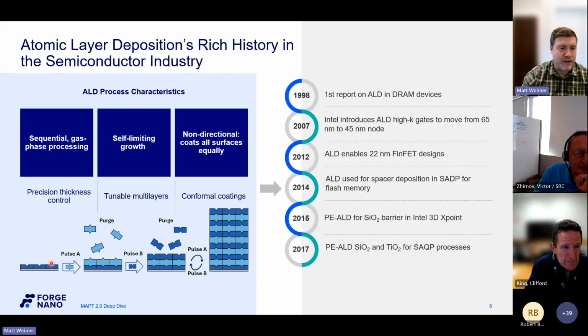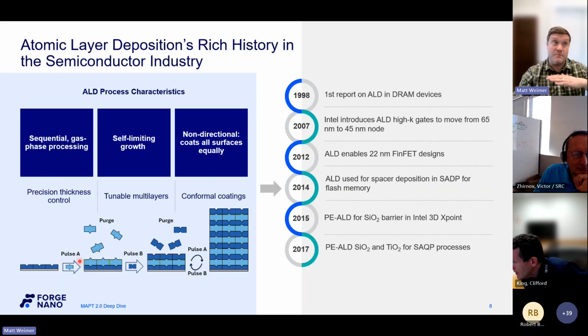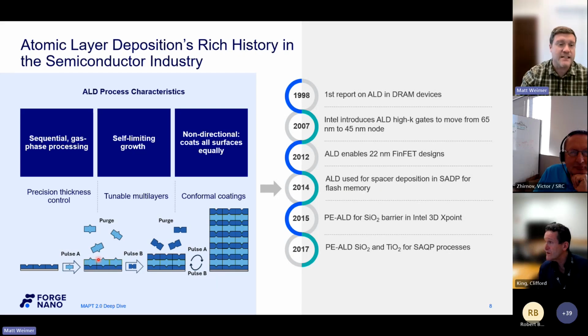So what that looks like pictorially here is you start with a surface that has some reactivity. You have these blue divots here. You bring in a precursor that has a reactive species that will react with that site. And in the best case, you get one monolayer of precursor. So now you have these little spikes on the surface. Those spikes are unreactive to the incoming spikes, right? Metal doesn't want to react with itself. So you can keep putting in more of this precursor without growing more film. You then have to purge away the remaining metal and the reaction byproducts.